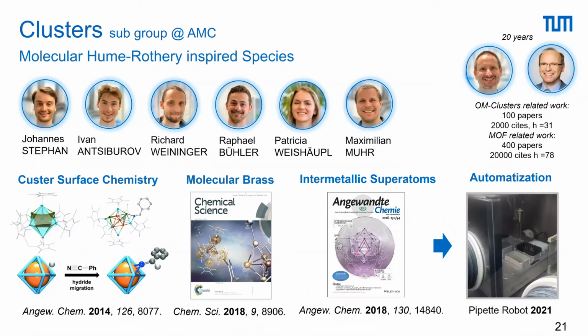And I'm pretty happy about the outcome of that, because at the early times when Christian joined, we wrote a DFG proposal, basically exactly proposing that we should be able to make these systems, all hydrocarbon protected, based on group 13 chemistry, low valent group 13 chemistry, and these aluminum organometallics should somehow act as surfactants to stabilize a metal-rich kernel. We wrote the proposal, and the referees didn't like it. I quote from their referee report: that sounds fascinating, but this will never work. Well, they were right. It took us almost 20 years, but it did work.